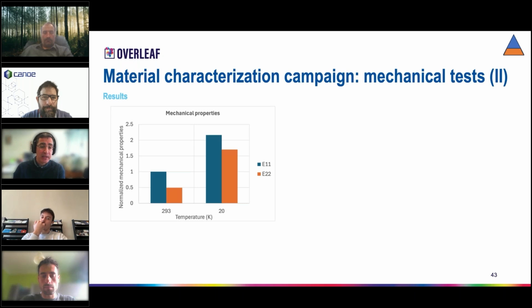From this test, we obtained some preliminary results. Here I have normalized with respect to the longitudinal modulus in the printing direction. Here we have a graph with two columns. On the x-axis, we have the temperatures. On the y-axis, we have the normalized mechanical properties. In blue, we have the longitudinal properties according to the printing direction. In orange, perpendicular to the printing direction. All these results are normalized with respect to E11 at room temperature.